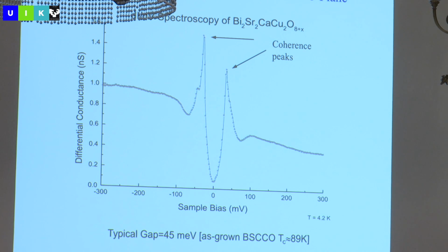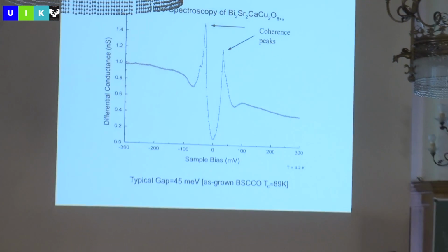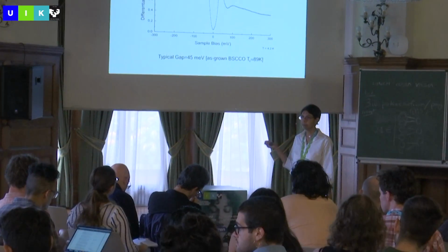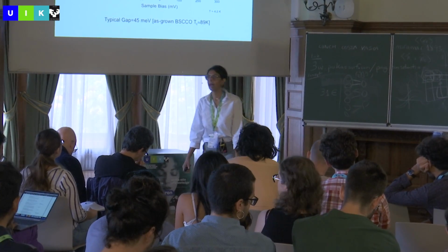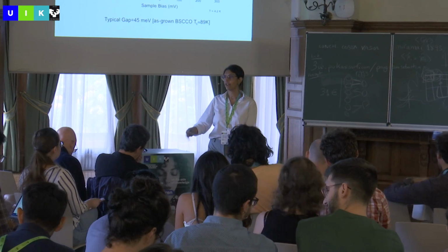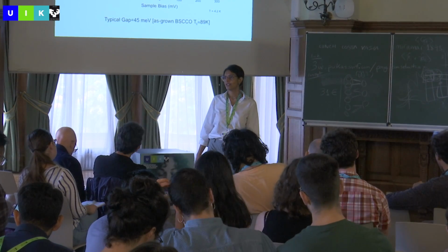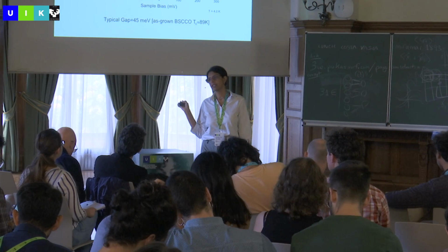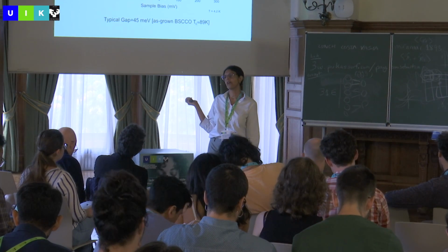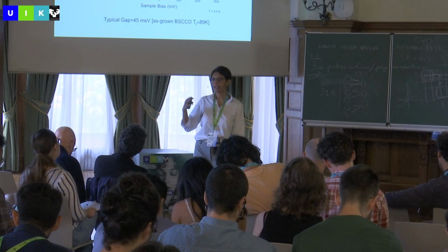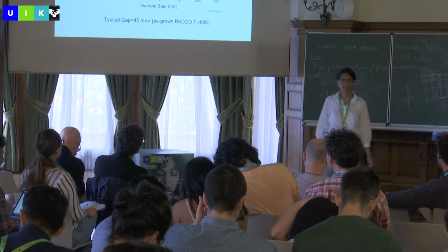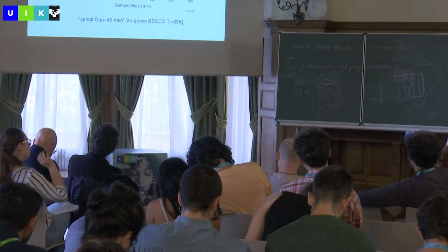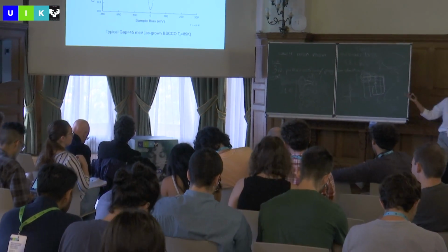Could you give the form of the shoulder? Does it give you information like what might be the process? Yeah, exactly, it does. Unfortunately, in this particular system, 2212, a phonon and a magnon, or a magnetic excitation, are very close in energy. So it's hard to tell. I believe actually that this is a phonon. So there is some strong electron-phonon coupling. You can track this as a function of temperature, and you might be able to ask if it sharpens or not and stuff like that.